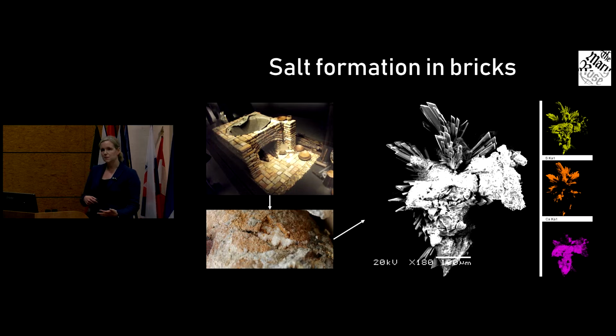We are also seeing some problems with sulfur in other materials. We have thousands of bricks in our collection, which can often be quite surprising to people. This was the ballast, but also made up the galley. There were 2 galleys on board the ship. And you can see the kind of salts that form, particularly when the artifacts are in high humidity.